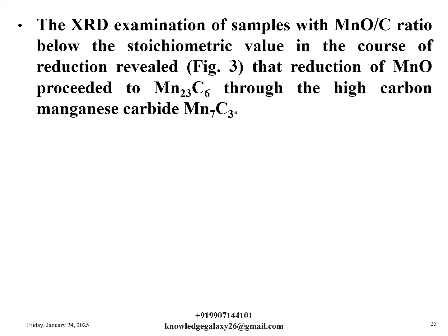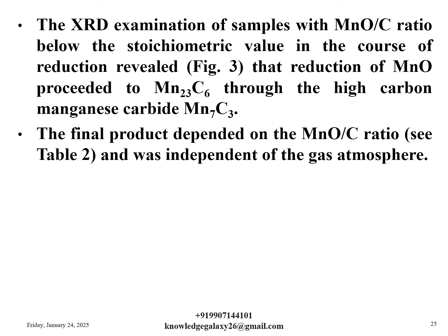The XRD examination of samples with MnO by C ratio below the stoichiometric value in the course of reduction revealed, which is shown in figure 3, that reduction of MnO proceeded to Mn23C6 through the high carbon manganese carbide Mn7C3. The final product depended on the MnO by C ratios, which is shown in table 2, and was independent of the gas atmosphere.